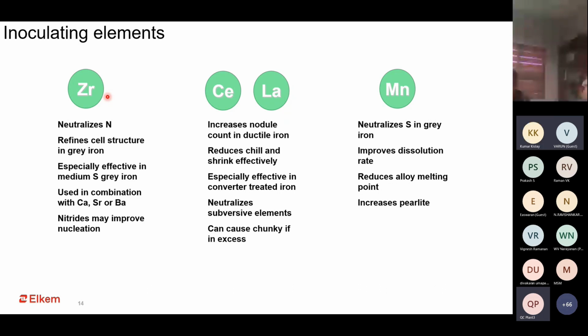One of the latest or modern inoculants has been the rare earth based inoculants. Rare earth primarily means cerium and lanthanum. Rare earth inoculants find application more in ductile iron castings. They help improve the nodule count substantially in ductile iron, and have a very good tendency to control carbides and shrinkage in the casting.